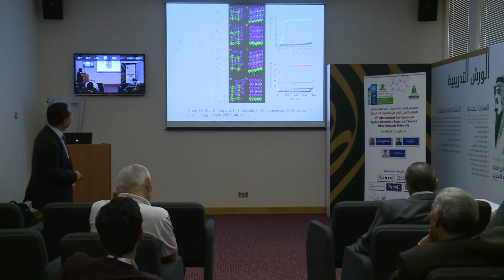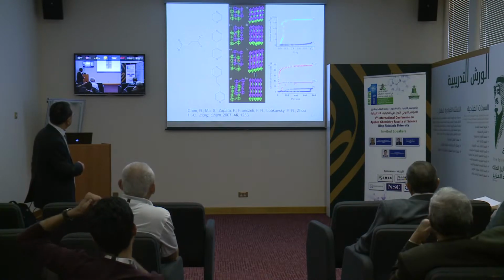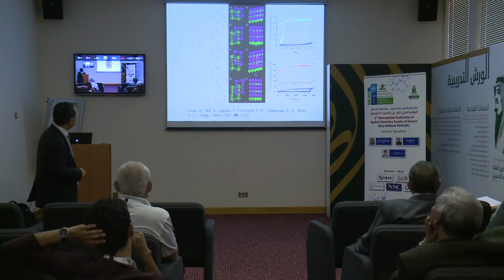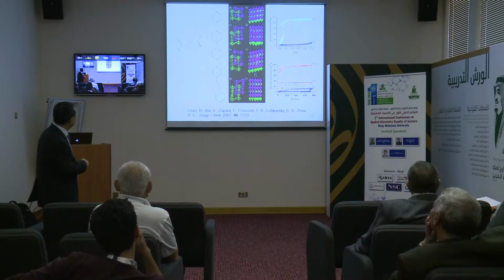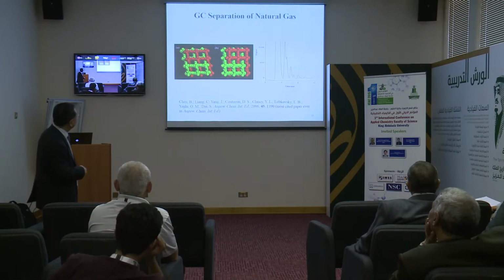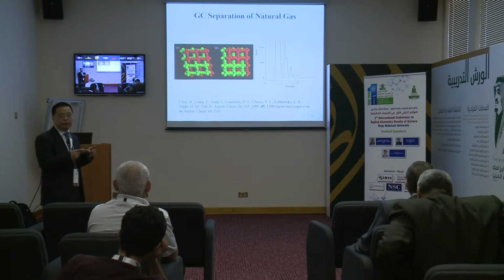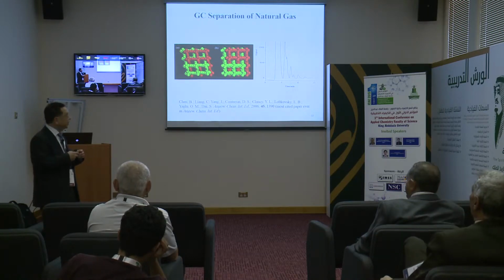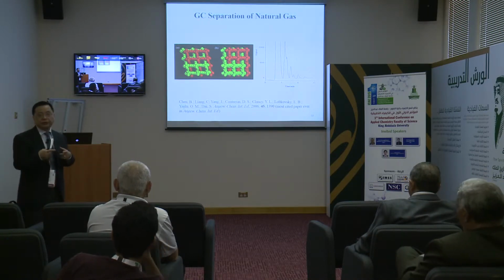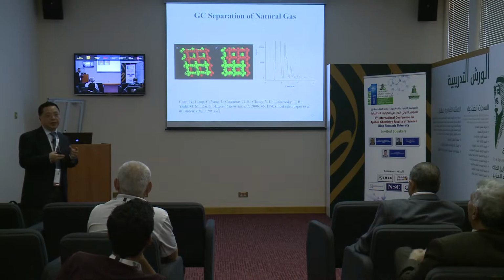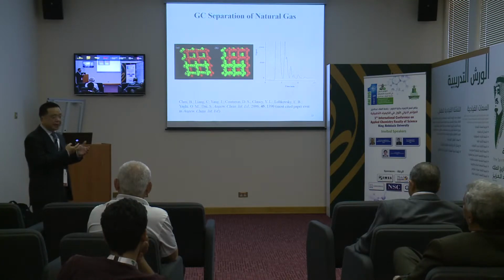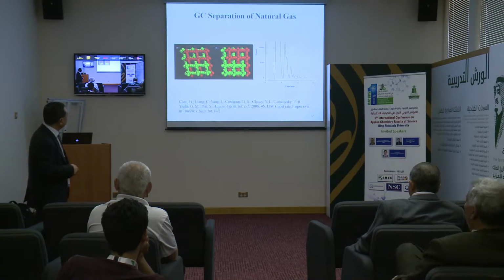So this is conceptual. And then we use another linker we call BDC, benzene dicarboxylate, with bipyridine. So the pore is a little bit larger, here about 4 angstrom. The 4 angstrom is basically comparable to the size of about 3.8 angstrom, so it is comparable with the linear part of an alkane. So we packed the column, and the column can easily separate the natural gas isomers.